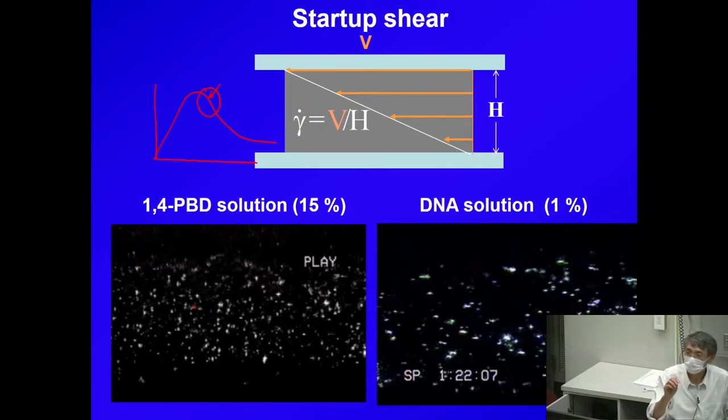If you prepare a sample less entangled with a smaller Z, you will end up observing only a homogeneous shear. In other words, this is a condition when the entanglement is rather severe; Z is quite large. If Z is smaller, you will have a boring result, where the movie will reveal that nothing is different from what I draw from the textbook. If you have only a movie like that, homogeneously sheared all the time, would you have as much insight about this overshoot point as this movie would tell you? The short answer is no.